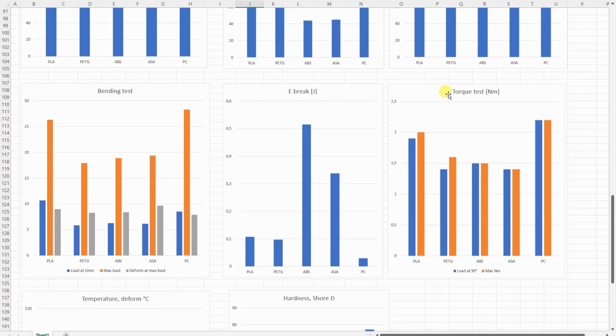Bending test and torque test, I noticed in earlier videos too that they are very similar. Maybe in the future I will place these two graphs next to each other. And yes, the PLA and polycarbonate were the strongest in these tests, but don't forget the PLA only at room temperature. If there would be some constant load, especially at a little bit higher temperature, in that case this would be completely different.